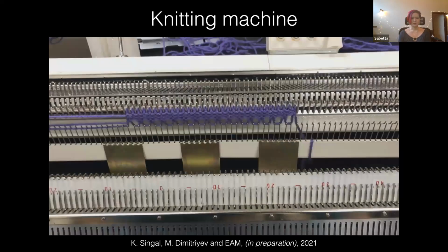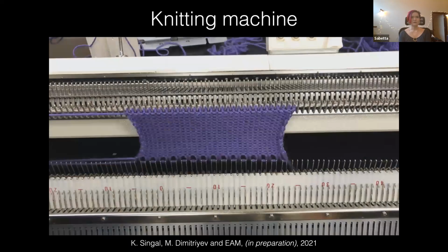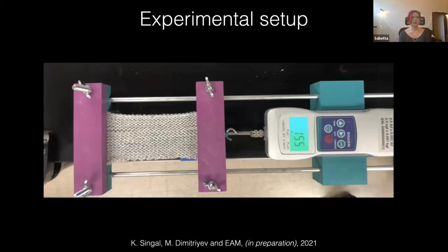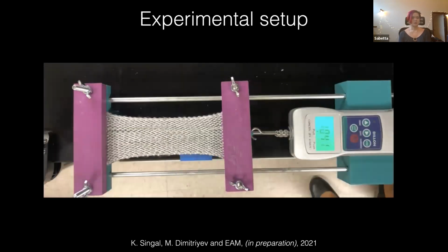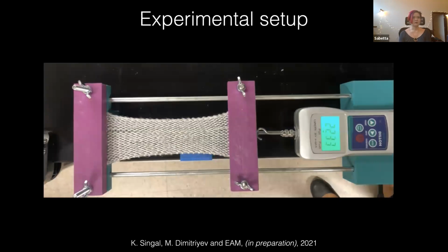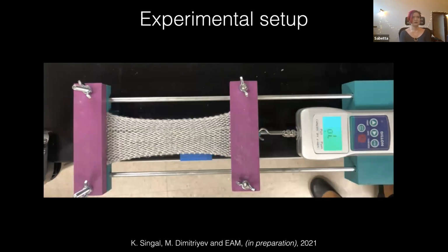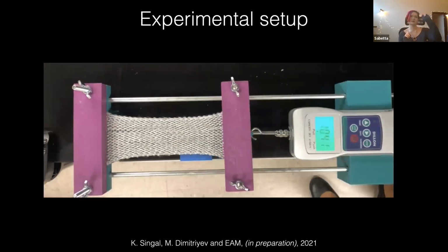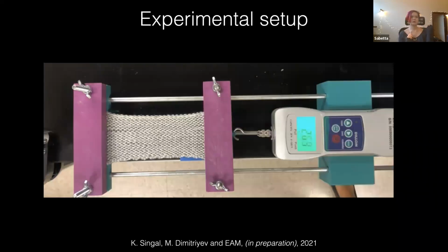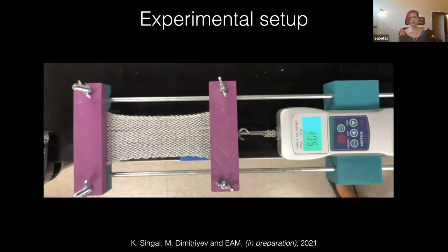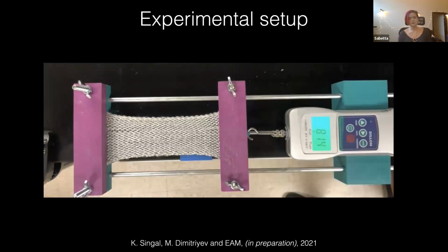And then from that, we've done stress strain analyses here. What Krishna does is she puts an array of pins in the textile, just the heads of pins, so they don't really affect anything, but they're something that the camera can pick up, and then uses those to back out the full nonlinear strain tensor.